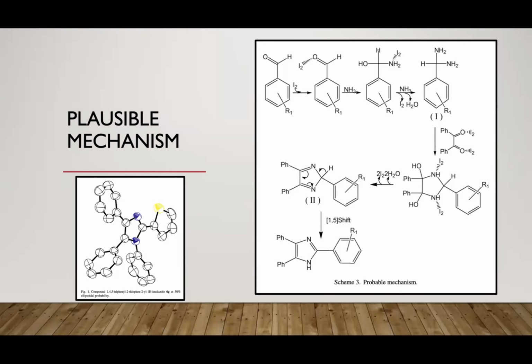The plausible mechanism which we predicted for the synthesis is that molecular iodine acts as a Lewis acid. Molecular iodine is capable of binding with the carbonyl group. This increases the reactivity of the parent carbonyl group, the aldehyde which we took, the aryl aldehyde. As shown in this slide, we propose that iodine facilitates the formation of a diamine intermediate by activating the aldehyde group, which under mild acid catalysis of iodine condenses further with the 1,2-diketone, that is benzil, followed by dehydration, which eventually led us to isoimidazole, which rearranges via a 1,5 sigmatropic shift to the required substituted imidazoles.